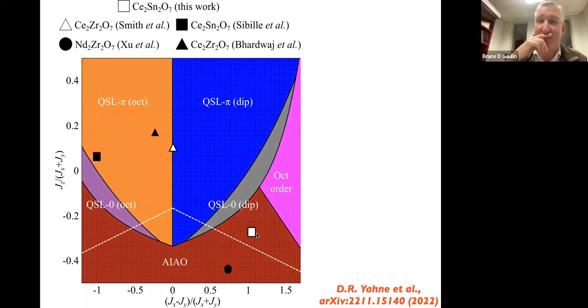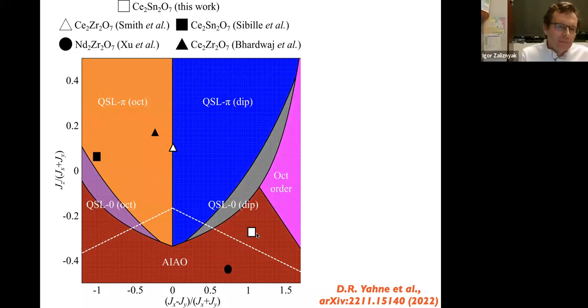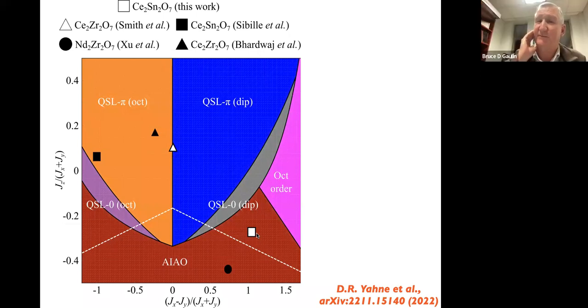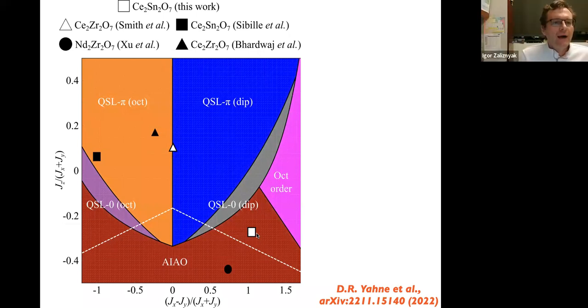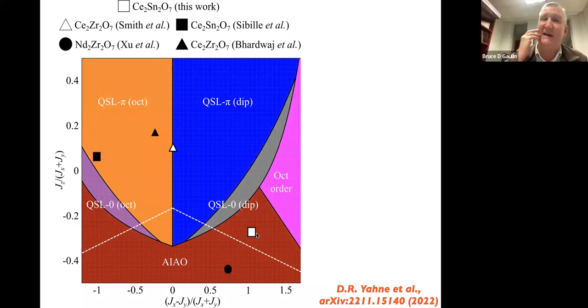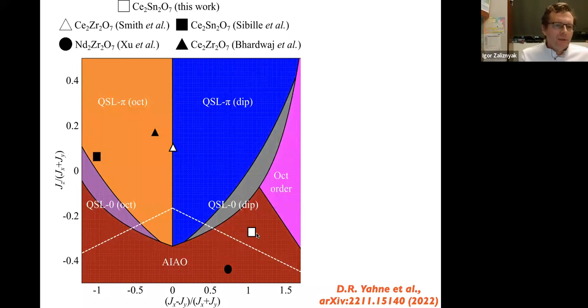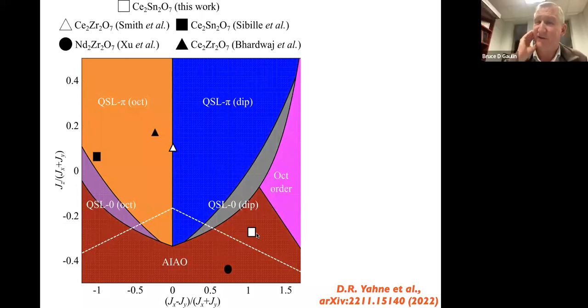But basically, you still could have some experimental upper limit. I mean, there are no zeros in nature, right? So what is that upper limit for G? Well, it's pretty well constrained. I don't have a good snappy answer for you, but it's constrained by both the relative intensities of the crystal field excitations and the fit to the Van Vleck susceptibility. Right. Maybe ESR should be done to actually figure that out. That's a good suggestion, actually.